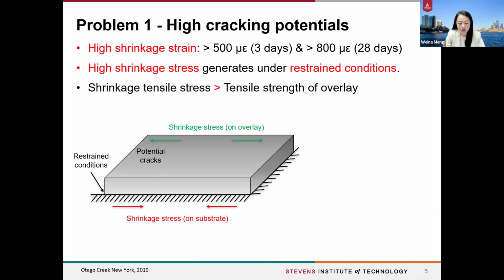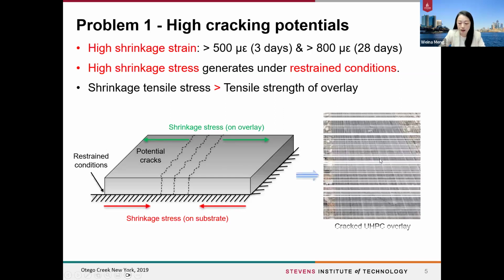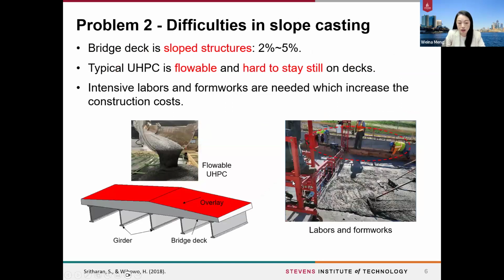However, there are several critical challenges for UHPC to be used as an overlay. First, it has a high cracking potential, mainly because we use a high binder content in UHPC, and that results in high shrinkage at early age. The high shrinkage will introduce high tensile stress, and when it exceeds the tensile strength of the concrete, especially at early ages, it will crack the bridge deck overlay. The second big issue is the difficulty in sloped casting. The majority of bridge decks are sloped structures with a slope somewhere between 2% to 5%. But the typical UHPC, as you can see, is very flowable, so it could flow from the top to the bottom, and it is hard to stay on the deck. So intensive labor and formwork will usually be needed for this kind of construction.